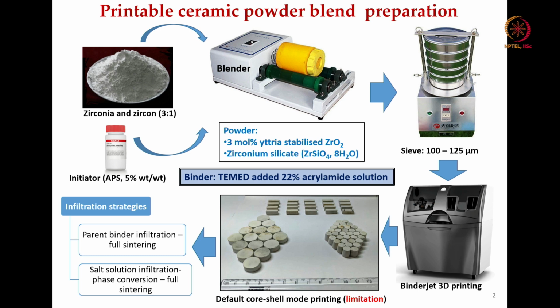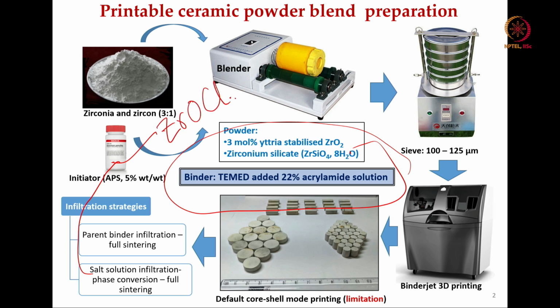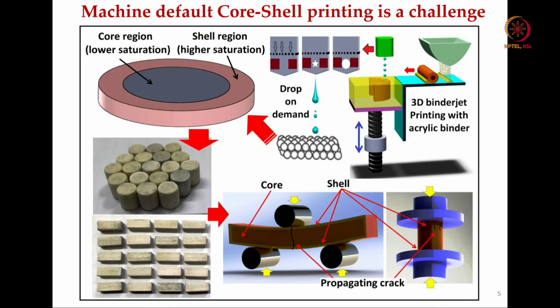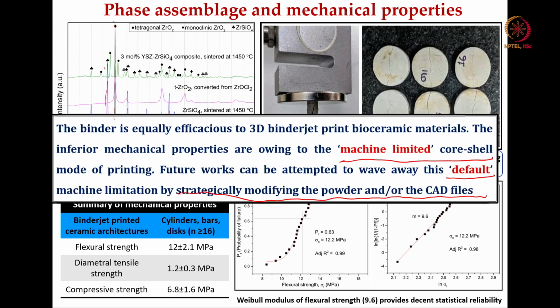One is the infiltration of the same binder solution, or a salt solution. That salt solution, as I mentioned to you, is zirconium oxychloride. Now, when you infiltrate zirconium oxychloride solution into the 3D printed construct and after that you sinter them, essentially zirconium oxychloride based solution is converted to zirconia. So, you get the same zirconia, but using a precursor salt solution. So, these are two approaches that one can take in binder jet 3D printing, particularly with these zirconia based materials.